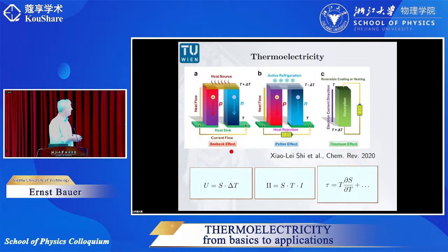So if we have a piece of material and have on the one side a large temperature and on the other side a small temperature, the hotter electrons will diffuse to the cold side. And because then there is an inequality of electrons between the upper and the lower side, an electrical field will be created. And this electrical field will prohibit that further electrons will flow from the hot to the cold side. So, it is just this electrical field which is responsible for this phenomenon of the Seebeck effect.